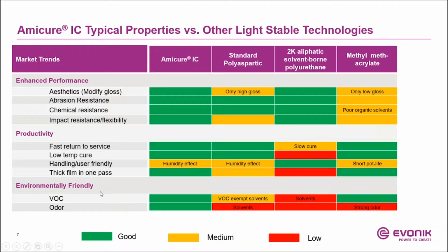Finally, I get into the environmental friendliness of these coating systems. I have the polycarbamide for VOC and odor as green. As I mentioned, the polyaspartics, which I'm comparing against, and polyurethanes are solvent-borne. You can use VOC exempt solvents, especially in the US, for polyaspartics. So you can claim that it's VOC free, but you still will see they will have some odor. And same with polyurethanes, because you're using solvents, they have odor, and again, they have high VOCs. MMA, in general, has low VOC, but as you know, MMA does have a very strong odor. So you can only apply where you have very good ventilation. It limits its use in indoor type of applications.